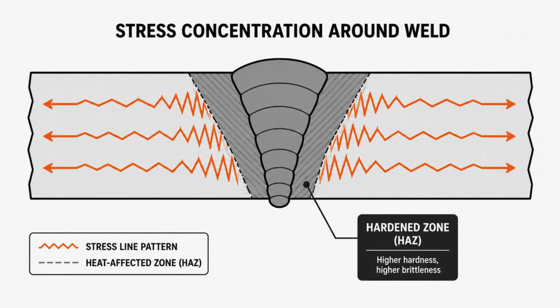Welding a joint doesn't just fuse metal, it leaves behind residual stress and a hardened, brittle zone right next to the weld. PWHT exists to undo both, before that vessel ever sees pressure.